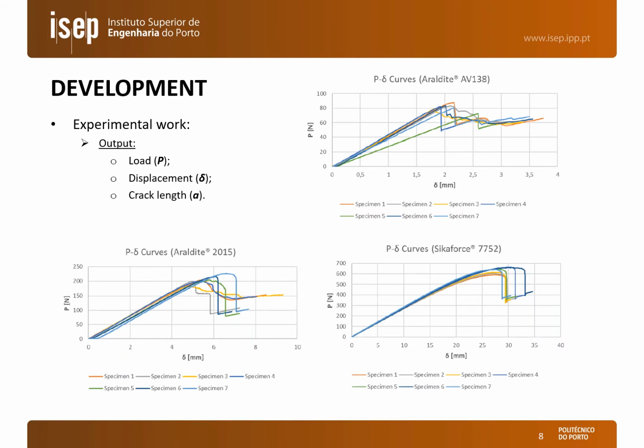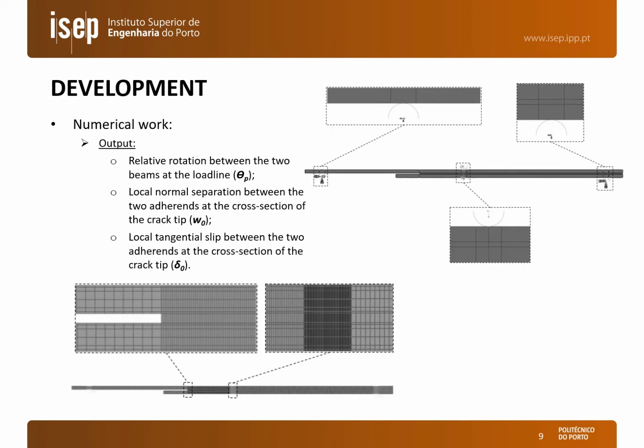Regarding the development of this work, we begin by showing the experimental load displacement curves for the three adhesives. We tested 7 specimens for each adhesive, and as you can see we have a good correlation between specimens of each adhesive, which is always an important feature to mention.